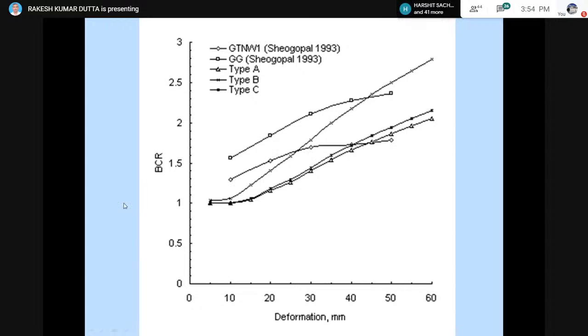So that means these products are equally good in comparison to the polymeric material used by Shiv Gopal in 1993. The reason is that they give the same level of improvement in the bearing capacity, in terms of percentage improvement, because BCR is a dimensionless parameter. If you make the comparison, the level of improvement is going to be similar in both situations. So this is the main conclusion drawn from this particular study.